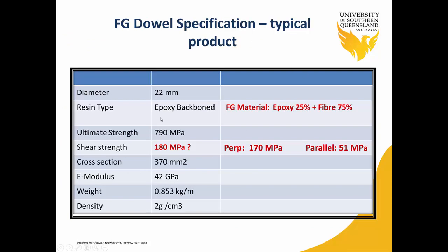Fiberglass dowel specification, typical specification is as follows. As I said, the diameter is around 22 millimeter. Resin type is epoxy. Ultimate tensile strength is 790 megapascal. Shear strength is claimed to be around 180 megapascal, which we will investigate in detail in this study. Cross-sectional area is 370 square millimeter. Elastic modulus is 42 gigapascal, weight is less than 1 kilogram per meter, and density is 2 gram per cubic centimeter.